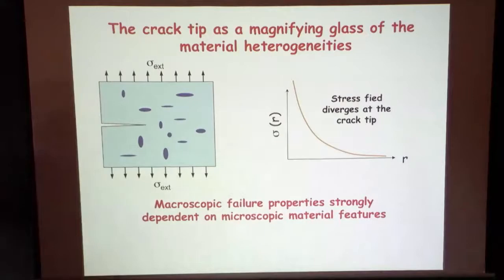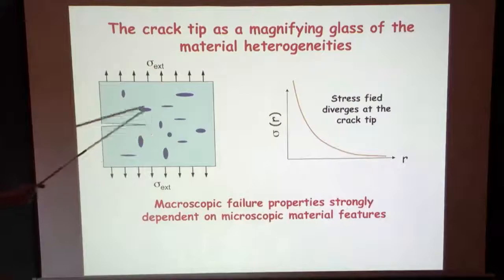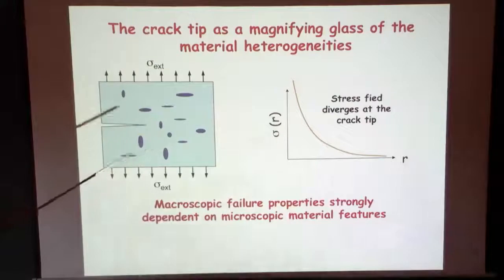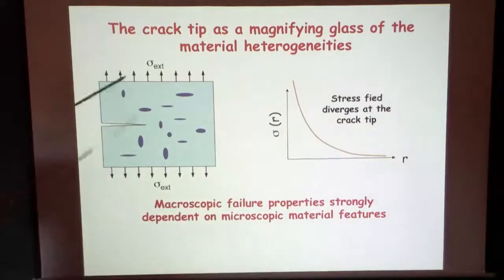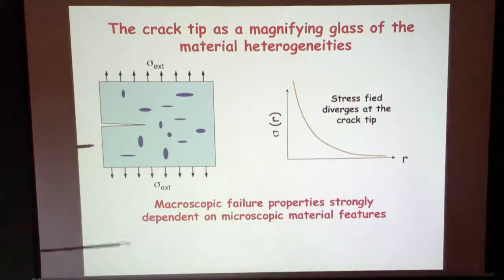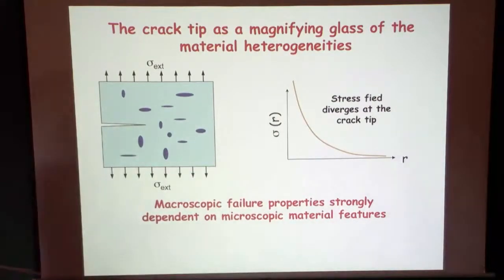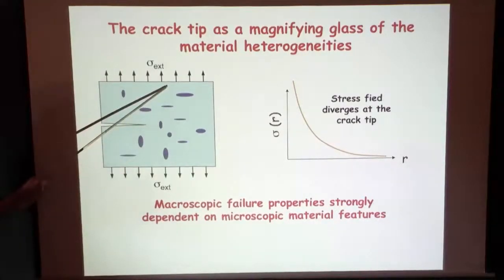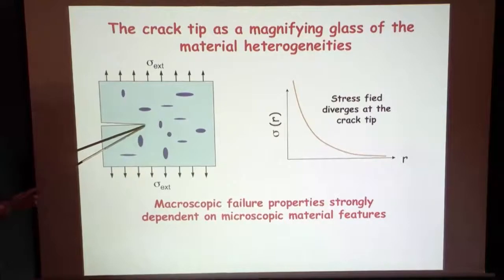If you now want to illustrate here how heterogeneity, how microstructure can be relevant in this problem, let's consider this kind of idealized case where we have two phases, a crack propagating in a material with some heterogeneity, some toughness heterogeneity, or some elastic property heterogeneity. And the singularity at the crack tip is going to make this problem very, very difficult. And in particular, it's going to make the fracture response of the whole system very sensitive to what's going on at the crack tip.